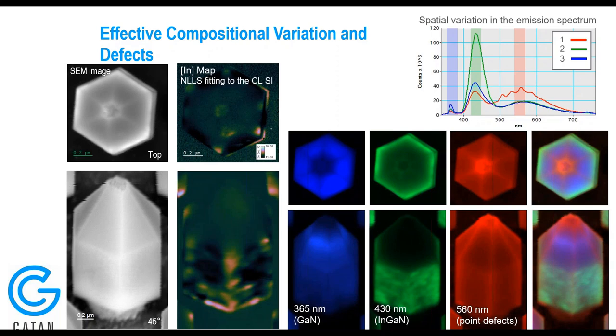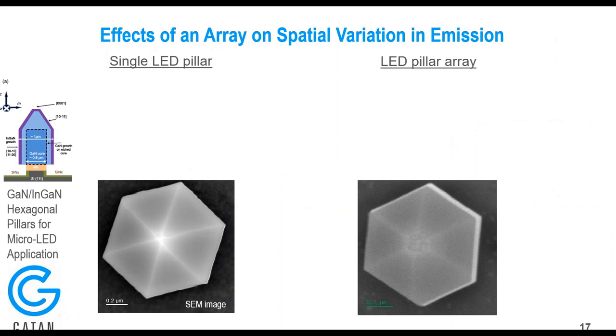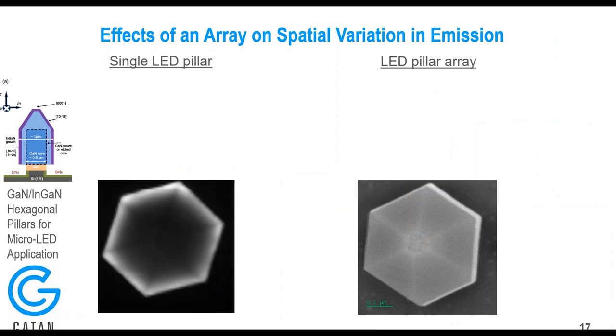Again, we can use nonlinear least squares fitting to map CL data to show us what the indium concentration is across the surface of these samples. And contrary to what we saw before, you can see the indium concentration tends to decay as we move towards the outside of the pillar. And that's not something that's obvious at this point. So then it makes sense to compare these sorts of effects and determine what effect the array is having on the emission characteristic.